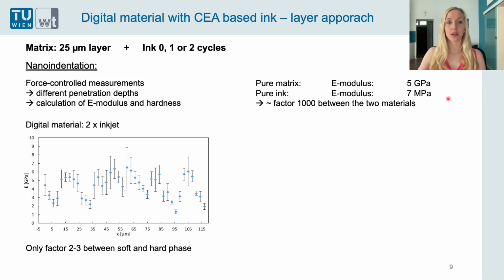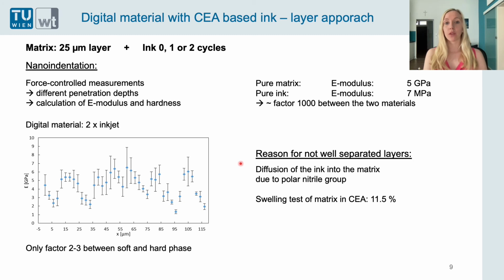And then the printed digital material was measured. Here the sample with 2 inkjet cycles is shown. And you can see there's only a factor of 2 or here 3 between the soft and the hard phase. And this is lower than I said in the beginning because we want to have a factor of at least 5 between the layers. And we think that the reason for the not well separated layers is the diffusion of the ink into the matrix due to the polar nitrile group of the cyanoethyl acrylate.